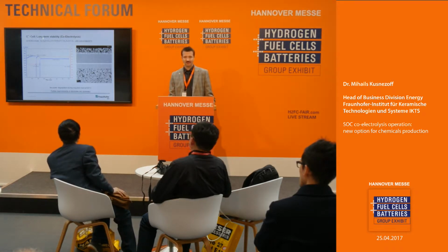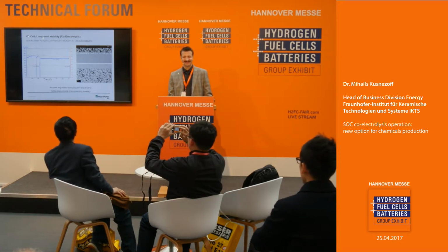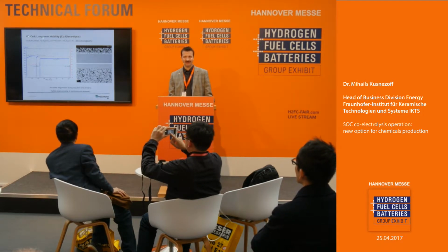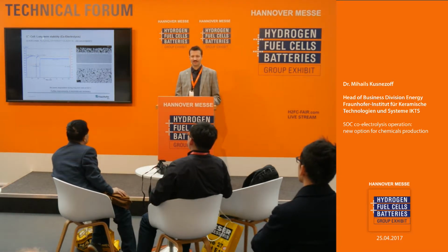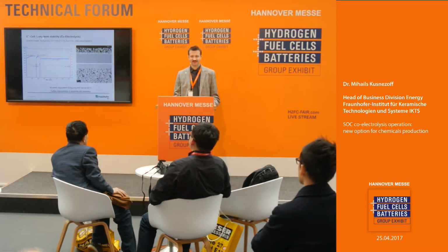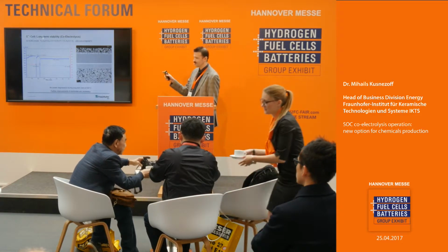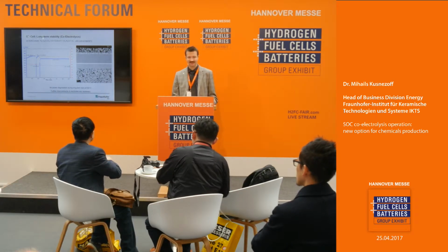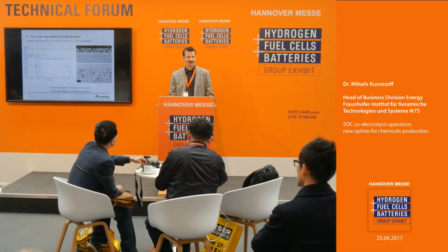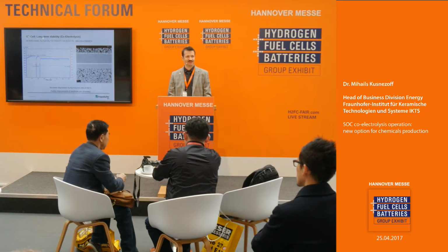Then we have observed very interesting phenomena. Depending on the temperature we operate the cell, we can see some short-term degradation or short-term effects for stabilizing the operating voltage. For example, at 800 degrees, we observe such saturation of the voltage, which takes place in the first, I would say, 100, 120, 200 hours. And if we increase the operating temperature to 830 degrees C, then we don't have such effects.